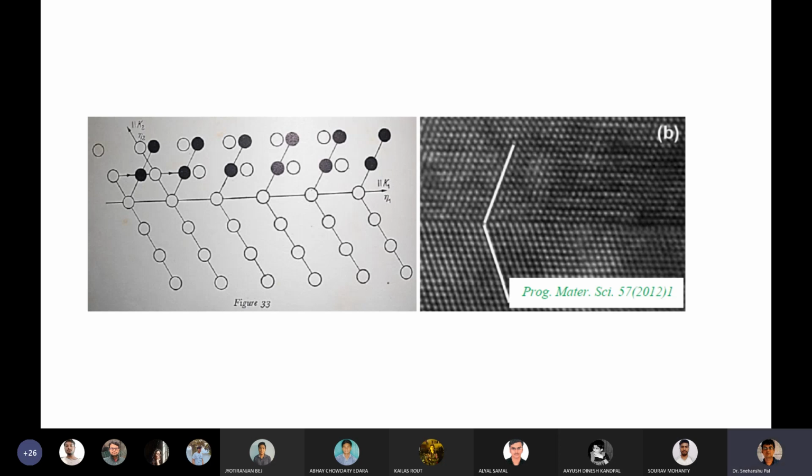This is different from what we see during dislocation slip, where the movement of atoms is a multiple of the lattice parameter or atomic spacing. But in case of twinning, atomic movement is less than one atomic spacing. You can confirm this distance by critically observing the picture presented in the slide.